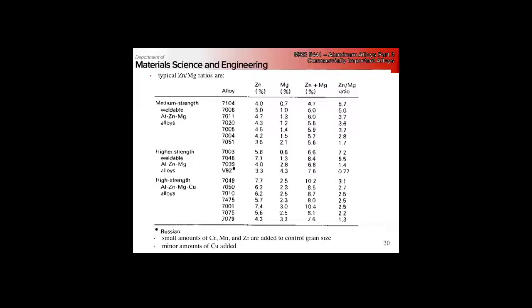The aluminum zinc ternaries are good because they're weldable, right? Once you start throwing copper in there, we lose the weldability. So we can generally separate out the 7000 series into medium strength weldable, high strength weldable, and then high strength non-weldable alloys.